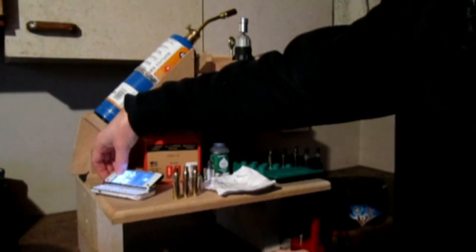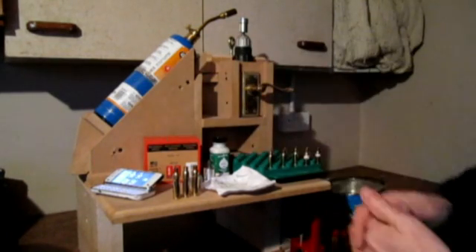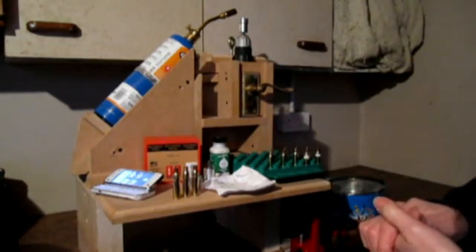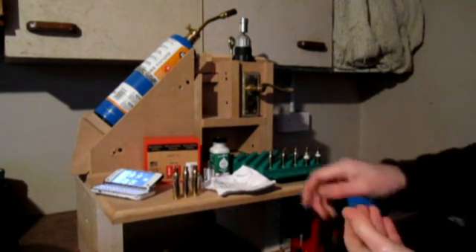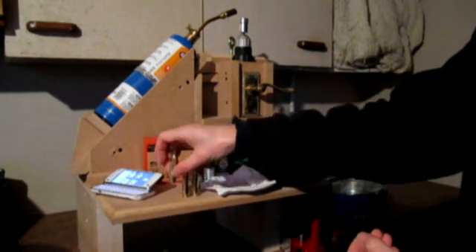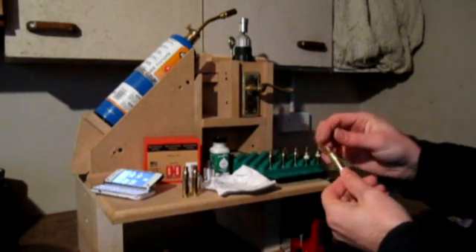I'll just stop my little clock. So we took on average between 17 and 20 seconds to anneal each case. If I go for maybe a 17, 18 second average, that should be adequate.